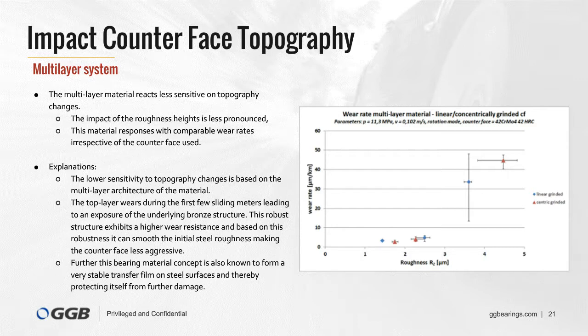How can we explain that this material is just less sensitive to a topography change? In one of the slides, I explained that this material has a multi-layer architecture. We know that the top layer wears during the first sliding meters. This leads to an exposure of the underlying bronze structure. And we know that this bronze structure is very robust and has a very high wear resistance. Further, this robustness helps potentially to initially smooth the steel counterface, making it just less aggressive.